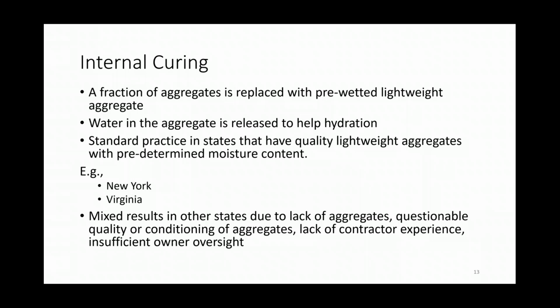This was very interesting. We spent a lot of time on this during the workshop. For some states, this is pretty much standard practice. New York and Virginia were 2 of those states, so they do this for all their concrete decks, and they've seen great results. But other states have mixed results with this. We came to the conclusion that the states that have good results must have good quality lightweight aggregates, and they're confident with the moisture content of the aggregates. Suppliers know how to store them. Versus if you have mixed results, you probably either don't have lightweight aggregates at all, or you're not sure about the quality of it, or the contractors are inexperienced.